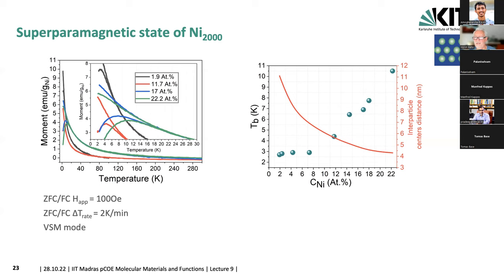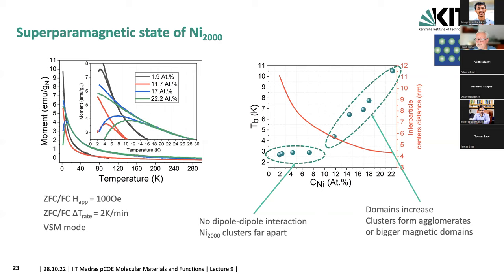So there is, highlighted in green, no dipole-dipole interaction because the clusters are too far apart. And here we have an increase in the domains as the clusters form agglomerates. They form magnetic agglomerates. So several of these clusters are now linked together, even though they are still separated by the matrix, but still they magnetically are interacting.